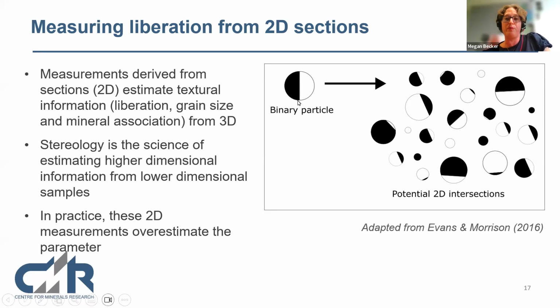So if one looked at this binary particle, 50-50, and you imagined this was a sphere, you could have any number of different intersections. You could have intersections like this one, the black one. So if we say the black is the valuable, that is fully liberated. That's very close to fully liberated, high-grade middling, whereas those white particles I would think are actually barren. This one I would call the black material locked, and this one I would call a middling, roughly half-half. So you can have any number of intersections, and that will cause the stereological error. And what we find is that these two-dimensional measurements overestimate the parameter.